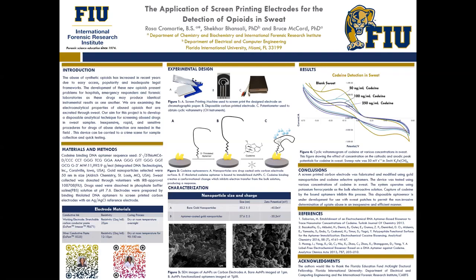For figure 2, you can see the schematic design of how my target binds to the working electrode of the screen printed electrode. I use nanoparticles, which are seen in the yellow. After allowing the nanoparticles to bind to the surface of the electrode, I then added a thiolated aptamer, which binds to the gold nanoparticle on the electrode surface. Then I added potassium ferrocyanide. The ferrocyanide is the electroactive solution to create the electric charge.